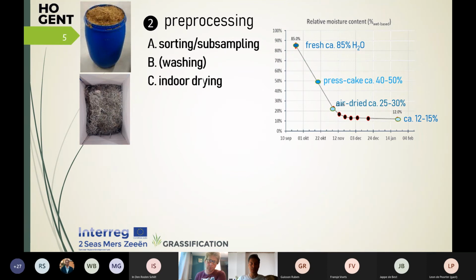Then the next step was the pre-processing. Unlike Mill Vision, we did not grind or mill our grass. We just reduced the moisture content after sorting and subsampling the grass. We had also, for the anaerobically digested grass, a washing step. And we performed indoor drying. So no, we did not use extra energy. We just let it dry indoors. And we managed to reduce the moisture content that way to about 12 to 15%. It fluctuated a bit at the end, depending on the air moisture.